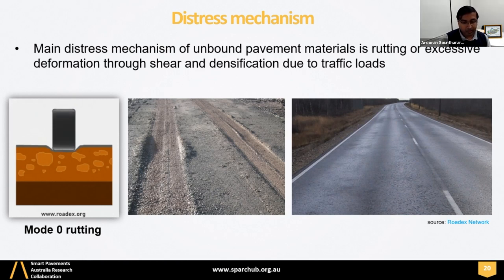It also causes the compaction material to stiffen, thereby spreading the load better. Right? As the shakedown occurs, which indicates the more stable position of the aggregate, it becomes stiffer. So we shouldn't expect further rutting after mode zero rutting occurs, if the pavement is constructed in good quality material and quality control is good.